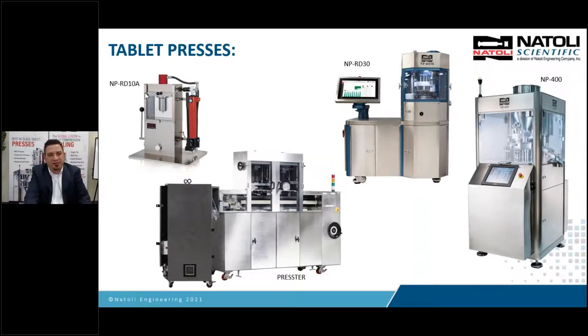The typical process is you start on a single station machine like the RD10A. This is a Natoli system. This only requires a very limited amount of material, let's say less than 1 gram. And you can compress tablets and measure the force and pressure, use the AIM data acquisition system to understand tabletability, compactability, compressibility, because the program will allow you to enter in the true density of your product. And if you know the tablet density, it'll calculate the solid fraction and porosity. But this machine, the way it compresses, it's not like the rotary. The upper punch comes down vertically, releases vertically, and ejects vertically. The rotary process, the punches are moving around a turret, and they're going through cams and rollers.